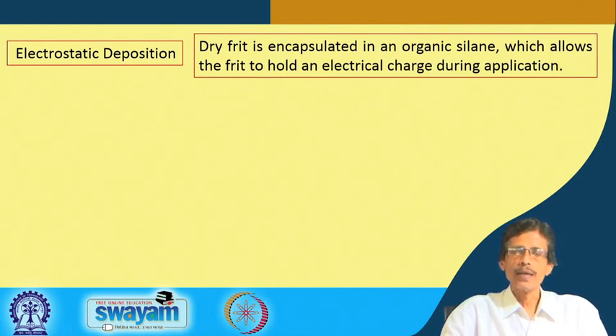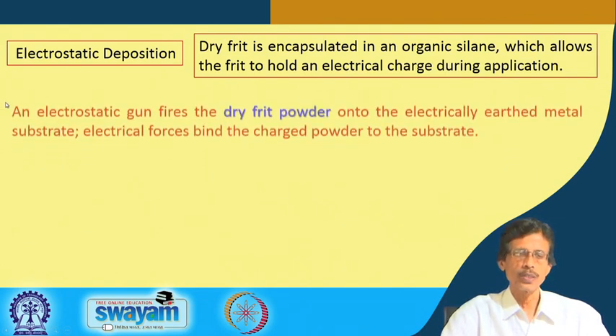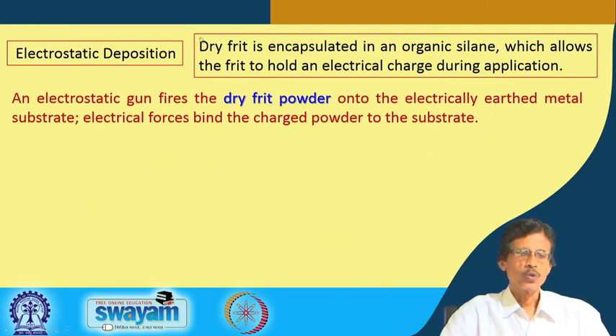So, dry frit is then encapsulated in an organic silane, which allows the frit to hold the electrical charge during application. If it is mixed with some organic silane, that material is in your organic part, the carbonaceous part. So, those organic silane molecules will be attached to that frit material, and during the electrostatic deposition process, it is then fired. An electrostatic gun fires the dry frit powder. So, if you have the dry frit powder, the electrostatic gun is utilized for firing that dry frit powder onto the electrically earthed metal substrate.